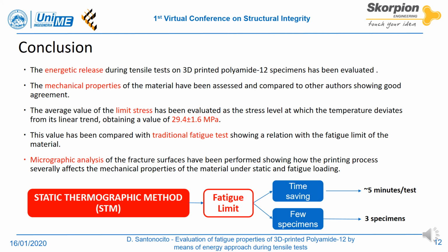The static thermographic method could be adopted in a rapid prototyping process as a fast test procedure able to predict the fatigue properties of the material from a conventional static test in a very short amount of time, 5 minutes per test, and with a limited number of specimens, even three specimens.